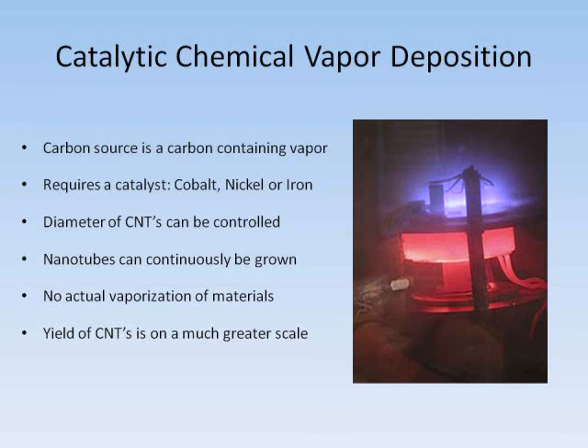The reaction chamber is heated to a very high temperature for the process to occur. In most cases of CNT production using the CCVD method, the most efficient conditions are no more than 700 degrees Celsius at one atmosphere of pressure. At pressures and temperatures above this, the decomposition of the carbon-containing gas, usually ethylene, results in unwanted soot in the reaction chamber among the CNTs.